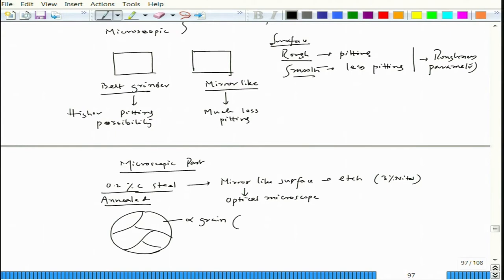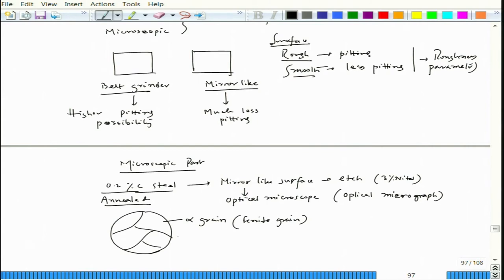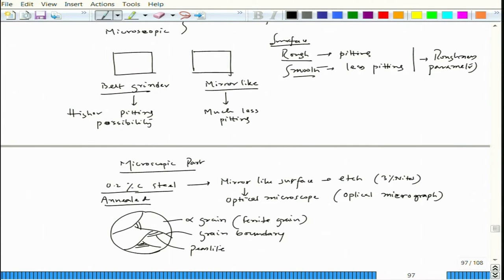The ferrite or alpha grains are visible, along with grain boundaries. Since it is 0.2% carbon steel, there will be some pearlite — a small amount of lamellar structure — also visible. This is the microstructure. This structure is microscopic in nature; unless you see it under an optical microscope after etching, it is impossible to see with the naked eye.